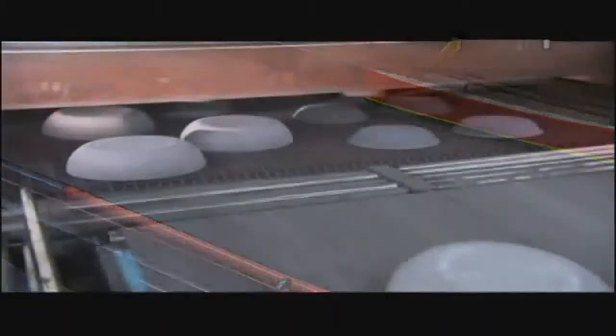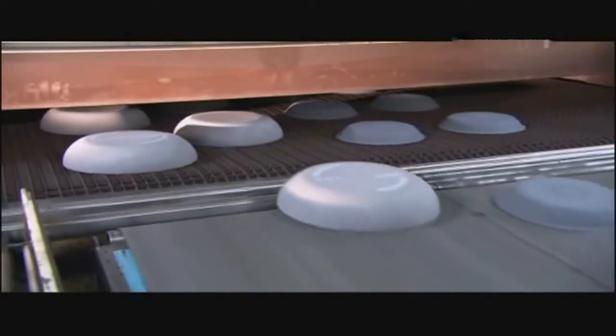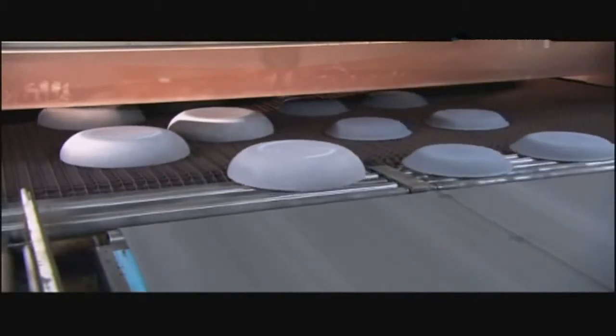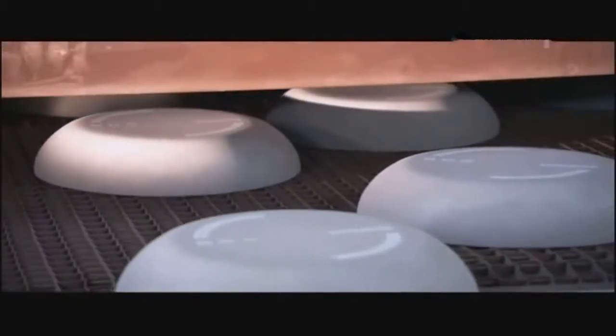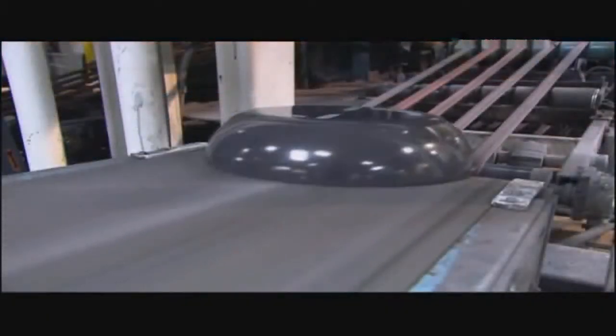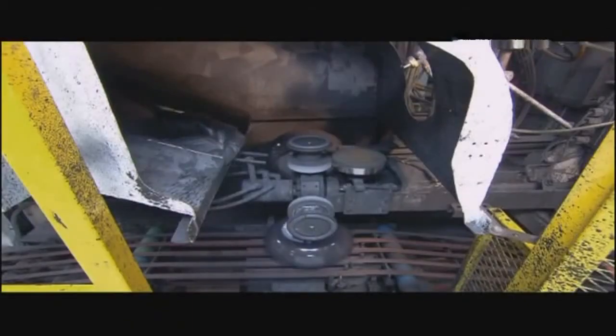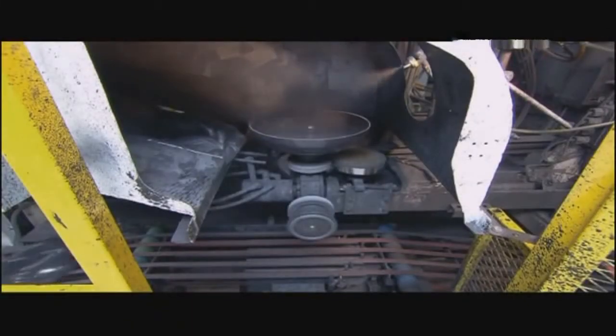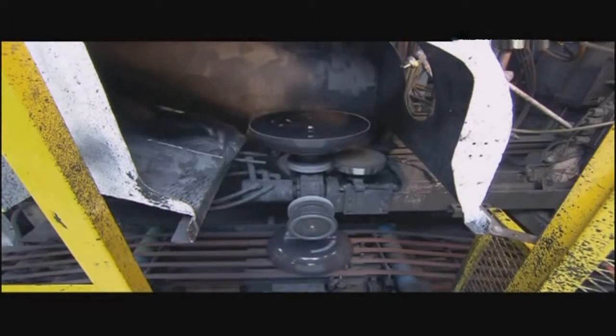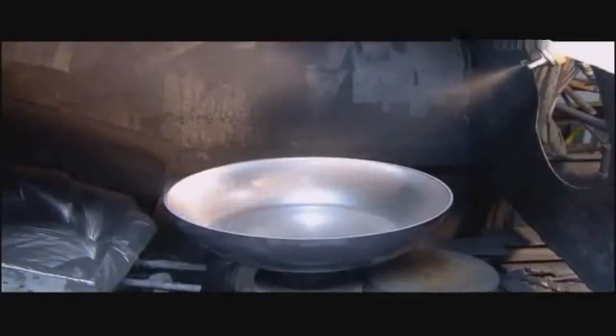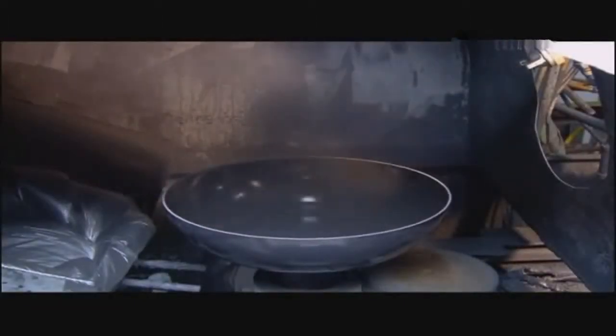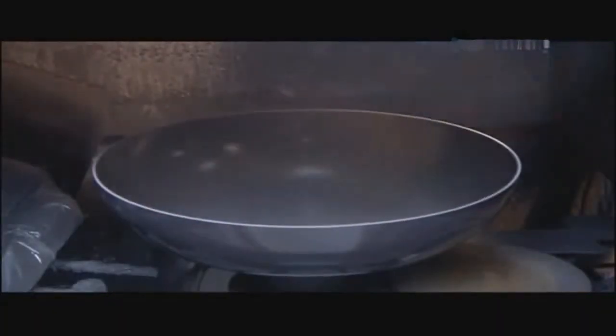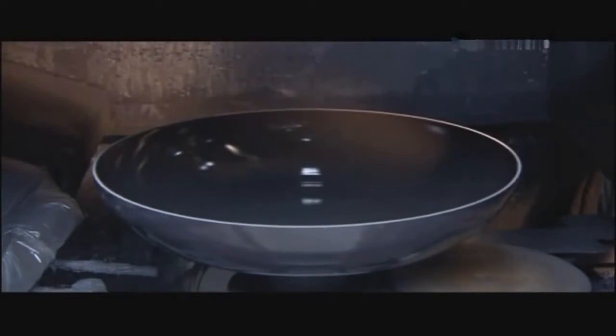They now enter a long curing oven, heated to 560 degrees Celsius. The cure toughens the enamel and deepens the colour so it turns grey and glossy. A suctioning device picks up the pan and turns it around for the inside coatings. A sprayer applies a special primer that will make the non-stick coating adhere to the pan. It then applies the non-stick coating. The pan receives 2 layers of this synthetic substance.